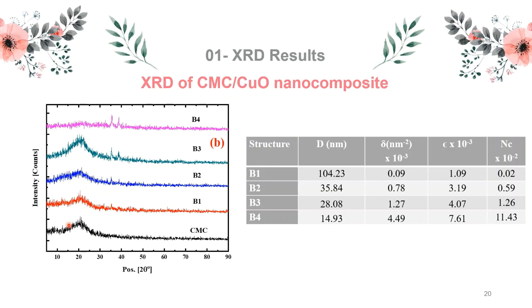It could also be deduced that the intensity of this peak decreases with increasing copper oxide nanoparticles, and it can be a result of the crystallite size reduction and microstrain generation. The addition of copper oxide nanoparticles as a nanofiller to a pristine CMC film was confirmed by the presence of a number of remarkable peaks of copper oxide nanoparticles, a decrease in the intensity of the CMC peak, and an increase in the copper oxide peaks with increasing copper oxide concentration.